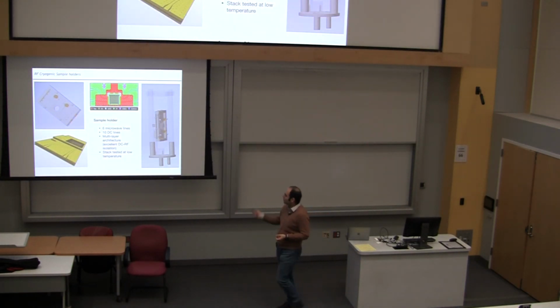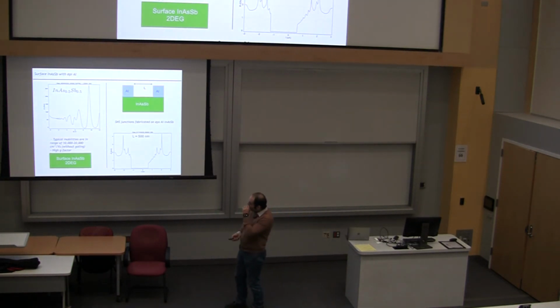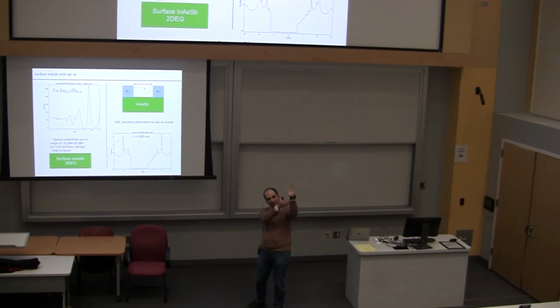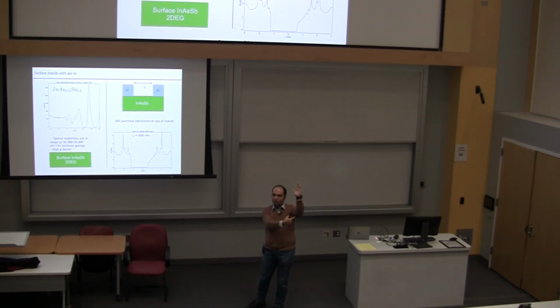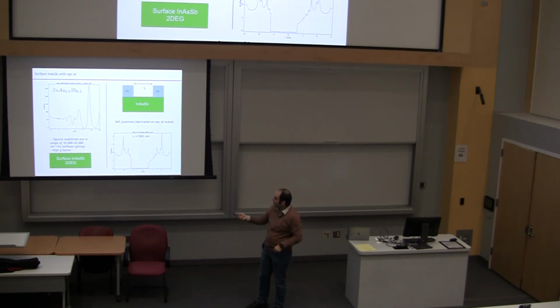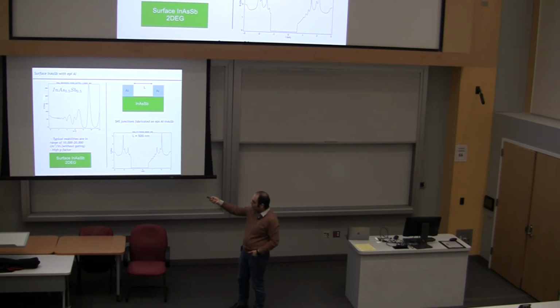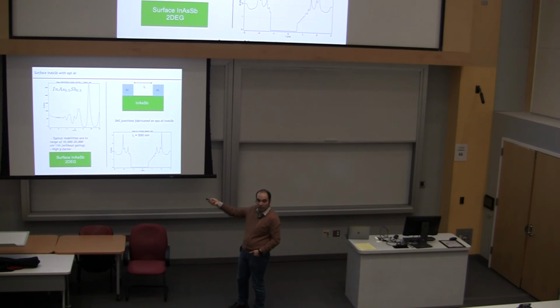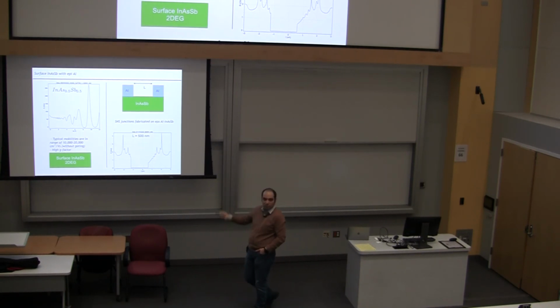So for measurement, you obviously go to dilution fridges. For this Majorana fermion, the g factor was important, right? A g factor of 15 was this slope. If it is 100, it comes closer. That means the magnetic field that you needed is going to go to a lower field, right? So one of the highest g factors among indium arsenide and antimonide III-Vs is indium arsenide antimonide, fifty-fifty. And we have grown this, and the quality, R versus magnetic field, looks decent. We have made Josephson junctions that show supercurrent and all that, so we have all of that.